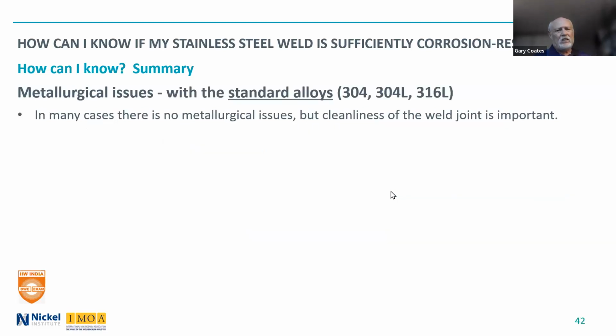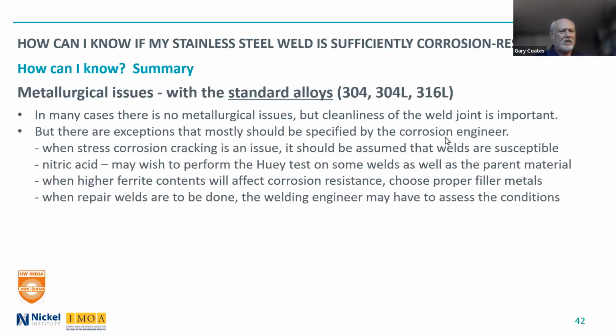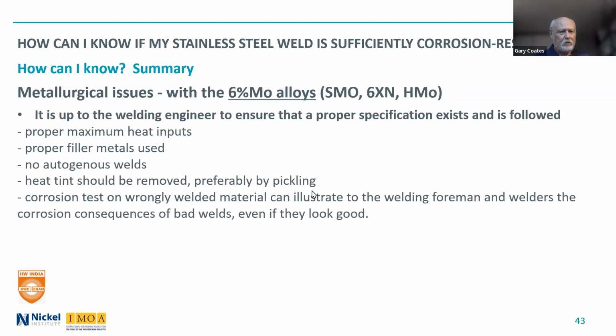With the standard alloys and the metallurgical issues, really there isn't a lot. Just we talked about nitric acid. We talked about a few cases where ferrite content may have an effect. And when I come to repair welds, you as a welding engineer may have to assess the conditions to see whether you want to use that matching filler metal or perhaps a slightly over alloyed filler metal.